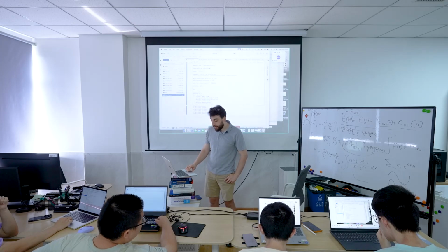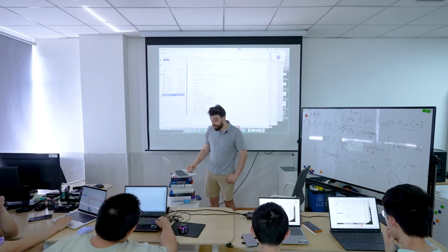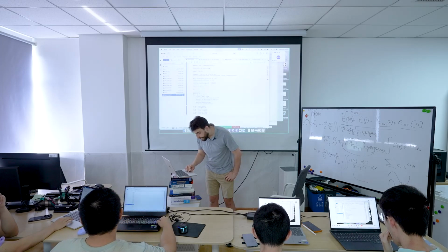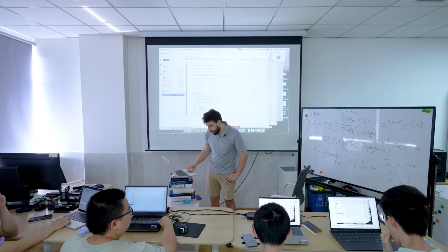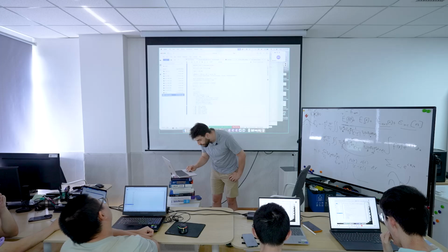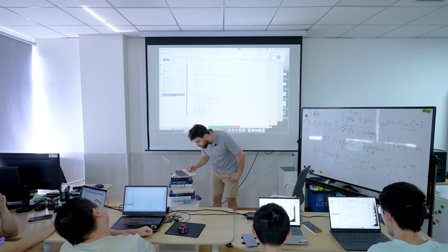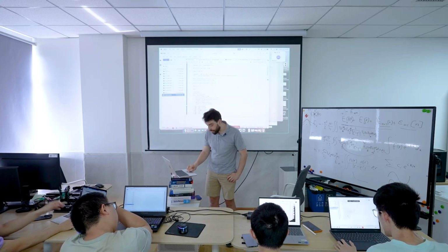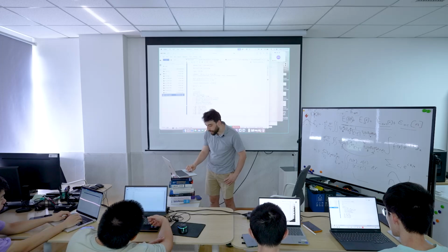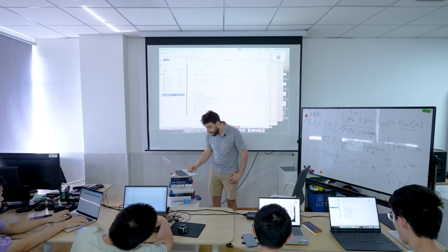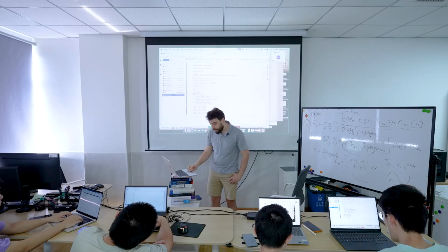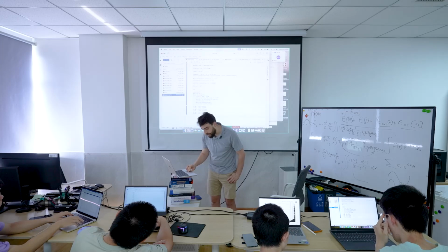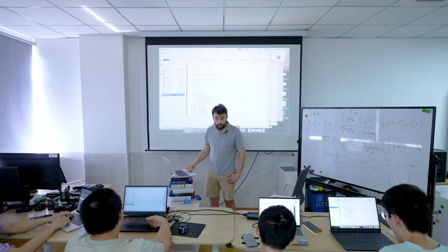What you can see here, if we look at the total energy, we can look at the difference between 300 eV and 400 eV, and we can see that the difference is about 80 eV. And then we go 400 to 500 difference, and we're looking at about 10 eV, and then about 2 eV between 500 and 600, and then we're down to 0.07 by the time we're at 600, 700 difference.